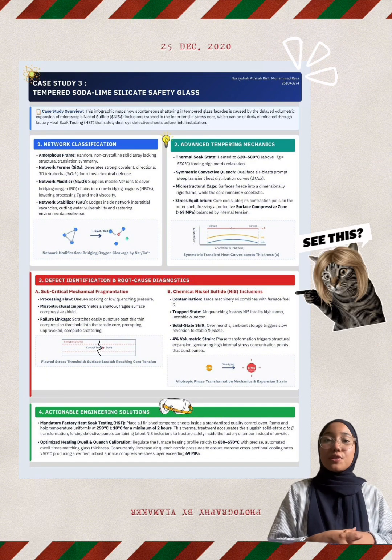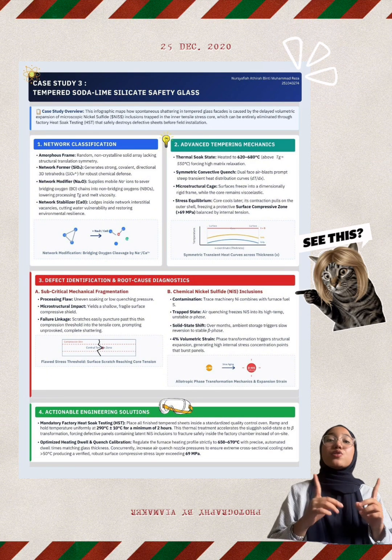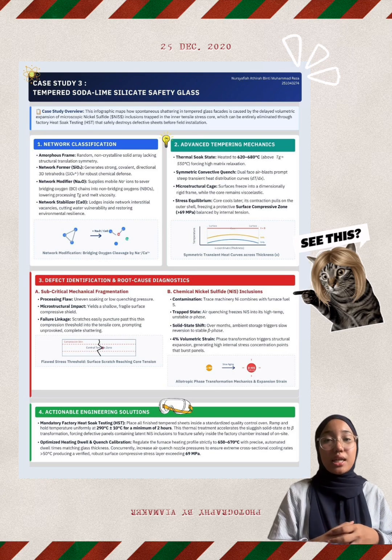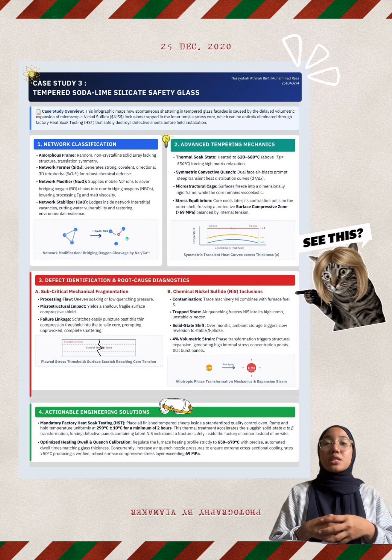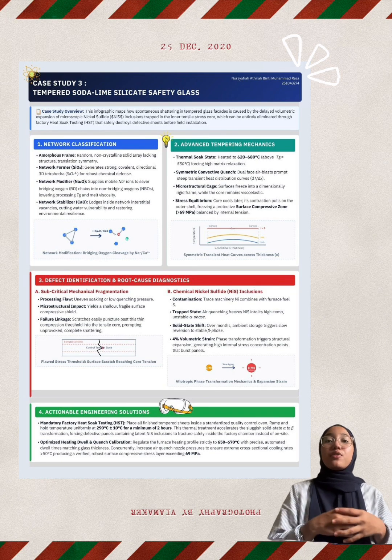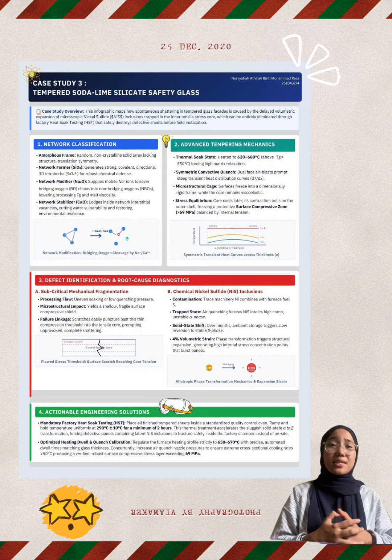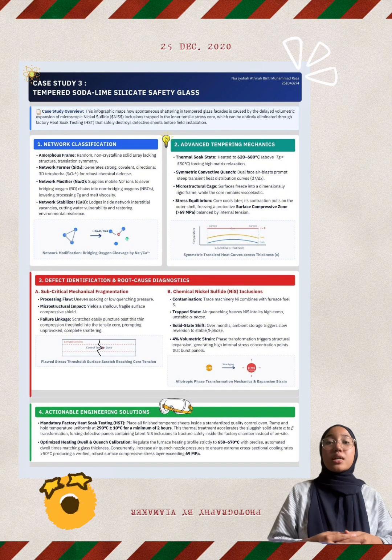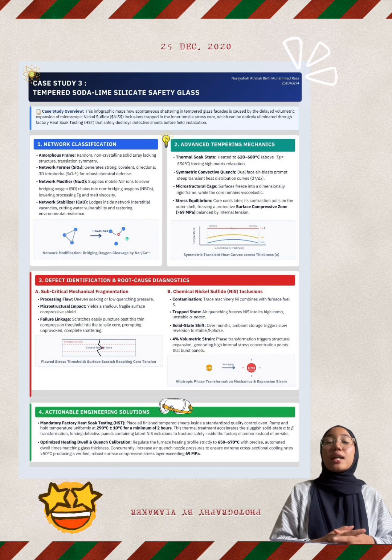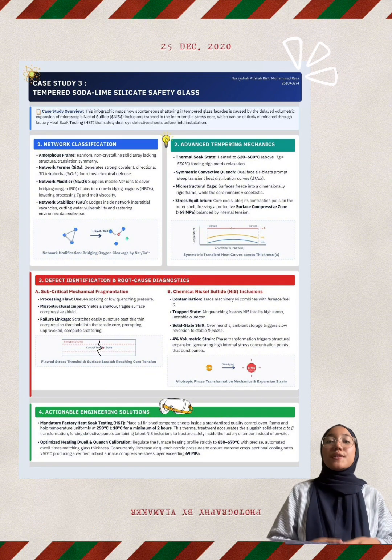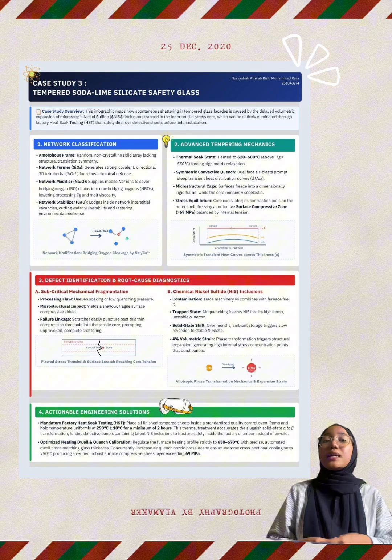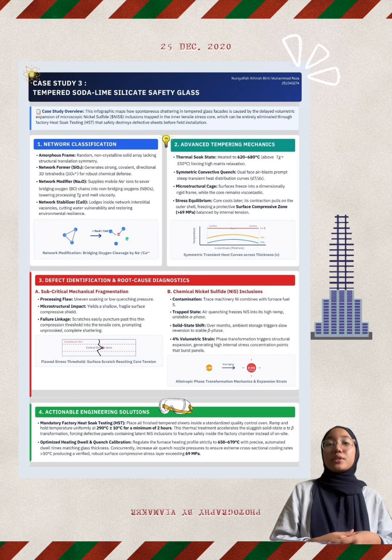Alright, so how do we solve a microscopic problem hidden inside a solid panel of glass? The definitive solution is mandatory factory heat soak testing, or HST. We place all finished tempered sheets inside a quality control oven and uniformly hold them at 290 degrees Celsius plus or minus 10 degrees Celsius for a minimum of 2 hours. This thermal treatment acts as an accelerator, forcing the sluggish, latent alpha to beta phase transformation to happen inside the factory. Defective panels fracture safely in the chamber rather than high up on a building facade.